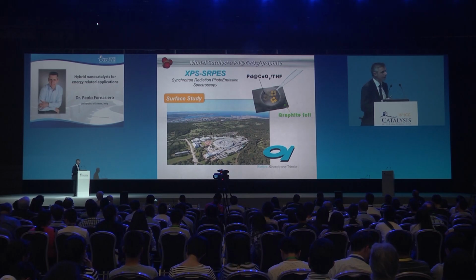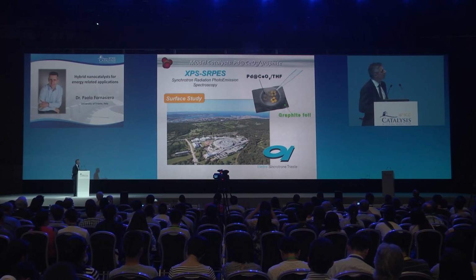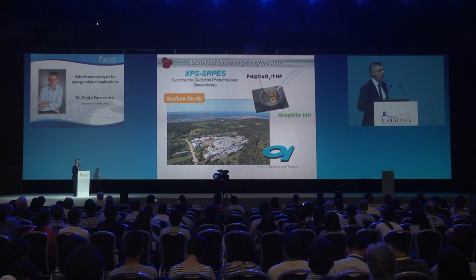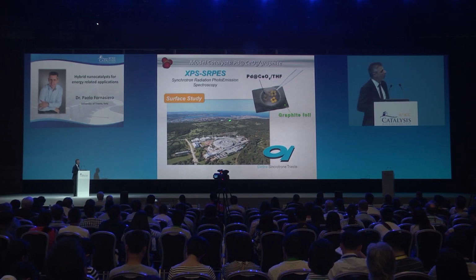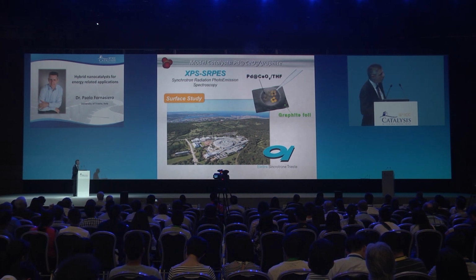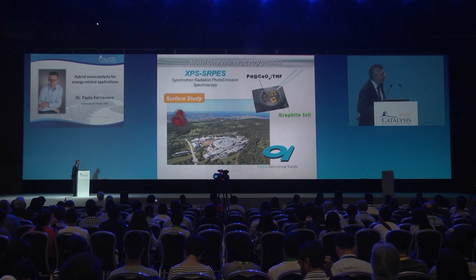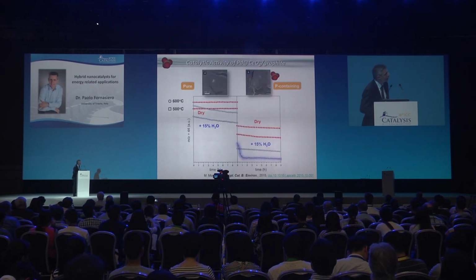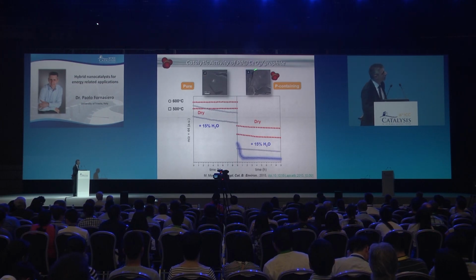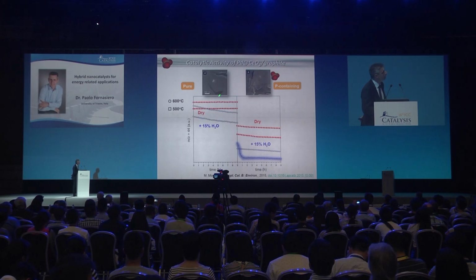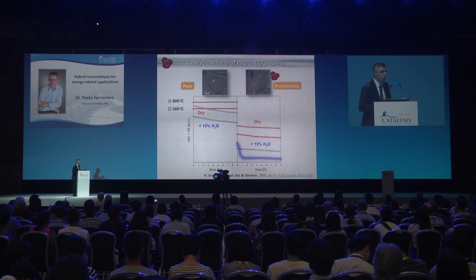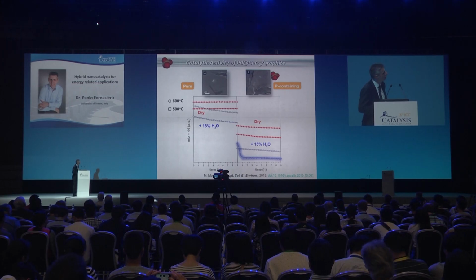To do that, in the case of phosphate from lubricant, we design model catalysts and deposit our units on a graphite substrate, and we perform what I call close-to-site spectroscopy, because this is my university here. This is the Elettra synchrotron in Trieste, so it took us a few minutes to go from the lab to the synchrotron. We prepared two types of samples: a model sample, palladium at ceria, deposited on pure graphite, and on phosphate-containing graphite as a controlled source of this poisoning component.